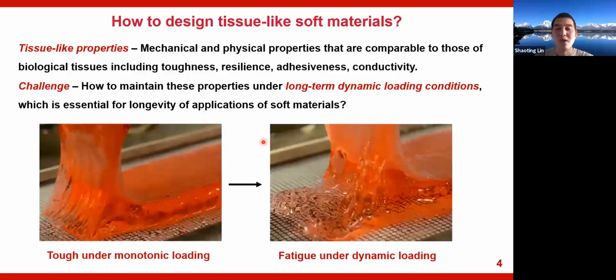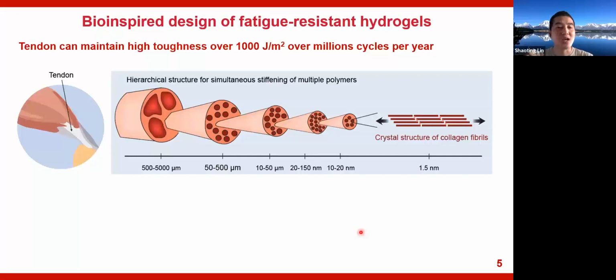Here is one example. People are able to make super tough hydrogel adhesion to diverse engineering solids. But once the hydrogel adhesive experiences cyclic peeling loading, it will gradually detach from the substrate. So the so-called tough hydrogel adhesion suffers from the issue of mechanical reliability. In contrast, biological tissues are able to maintain their robustness over millions of cycles per year. For example, tendon is a connective tissue that bridges the rigid bone with soft muscle. It can maintain high toughness over 1,000 Joule/m² over millions of cycles.